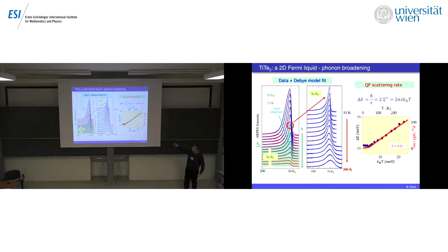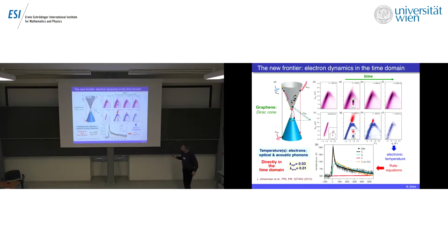And in this limit it is pretty much linear and proportional to the lambda parameter, to the mass enhancement parameter. So we can deduce from this plot the value of lambda for this particular material. Now, there is another way which we can use to measure directly the electron-phonon coupling, not in the energy domain, in the frequency domain, but directly in the time domain.